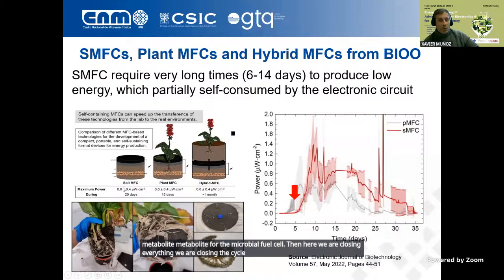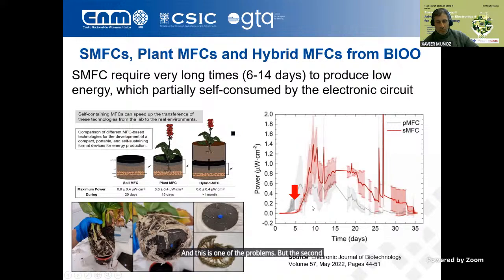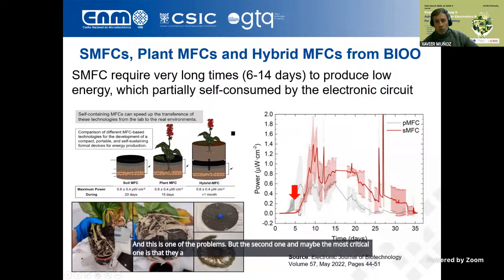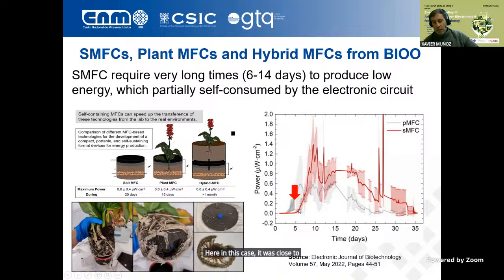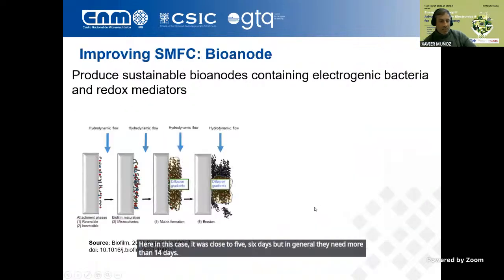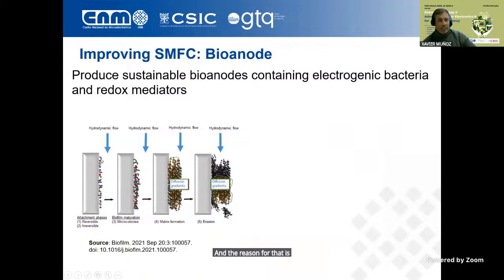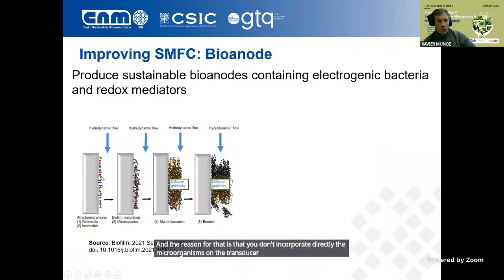And they are producing this kind of microbial fuel cells, and you can see that the power is not very high. And this is one of the problems. But the second one, and maybe the most critical one, is that they need a lot of time to produce some power. Here in this case, it was close to 5-6 days, but in general, they need more than 14 days. And the reason for that is that you don't incorporate the microorganisms directly on the transducer, but they just colonize it over time, producing what is called a biofilm.